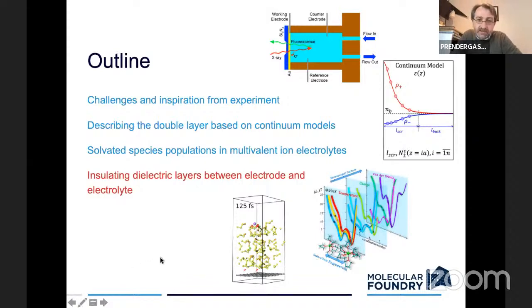So I want to talk a little bit about the existence of insulating layers between the electrode and the electrolyte. Okay, so the context for this is lithium sulfur. Long story short, lithium-ion batteries, they're great for cars maybe, but not so good for heavy-duty vehicles because the amount of weight that the battery occupies inside something like a truck begins to dominate the weight of the truck. And so you really need a high capacity and high energy density solution to that problem. Obviously, gasoline is the one we have right now, but lithium sulfur battery could supply that because it is about, let's see, a factor of 6 or 7 more capacity than a typical lithium-ion battery that's used in electric vehicles right now. Again, its lightness as well as sulfur could make it also useful for aviation.